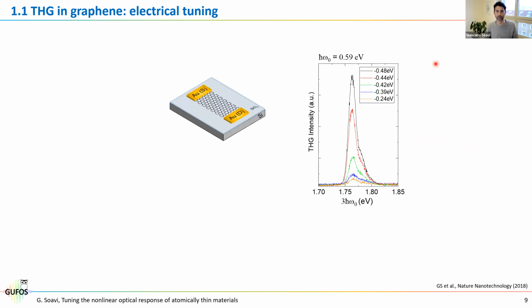So the first thing that we tried to do back a few years ago when we were still in Cambridge was to make a gate tunable device, so a graphene field effect transistor, and try to prove that we can actually move in and out from these multi-photon transitions in graphene. So the device is simply graphene on a silicon dioxide. So this is a backgated device. And what we do now is we apply a gate voltage to the silicon, we change the doping or the Fermi energy, we shine light at h bar omega, and in our case, h bar omega is 0.6 electron volt approximately. We look at the third harmonic that is at 1.8 electron volt, as you see here, and then we see how the third harmonic changes as a function of the gate voltage, or if you want, as a function of the Fermi level.